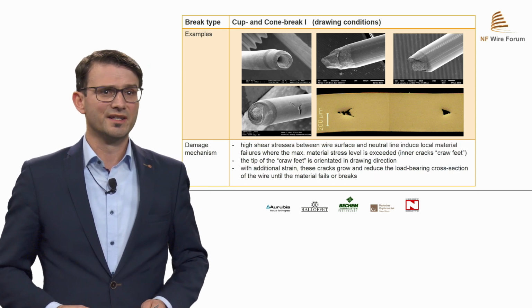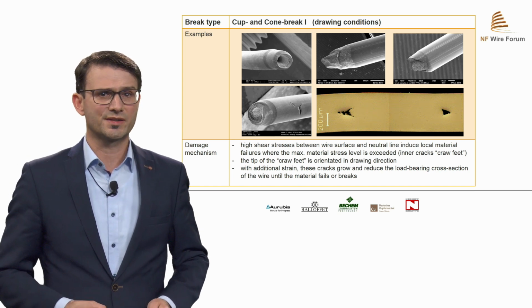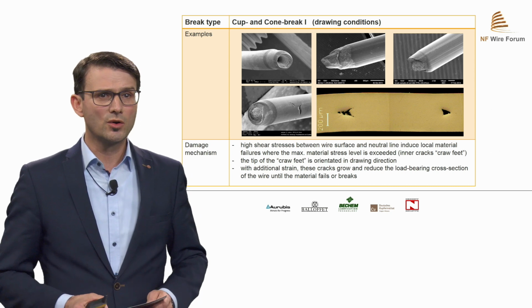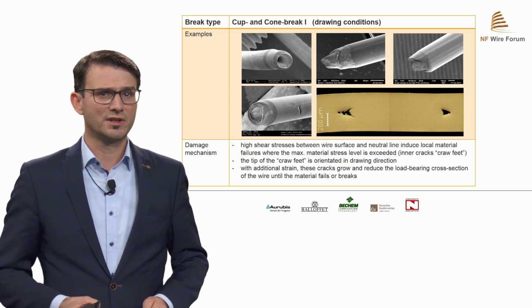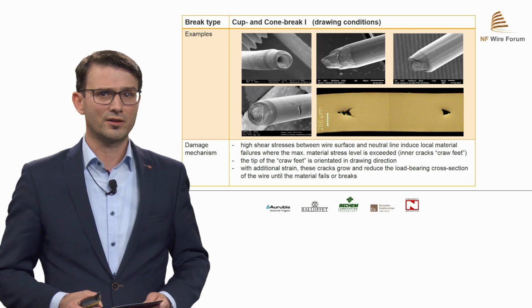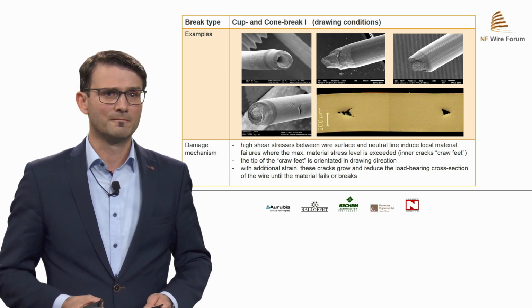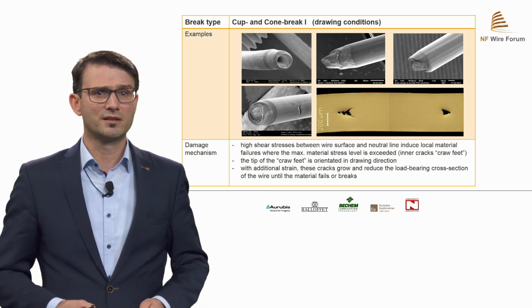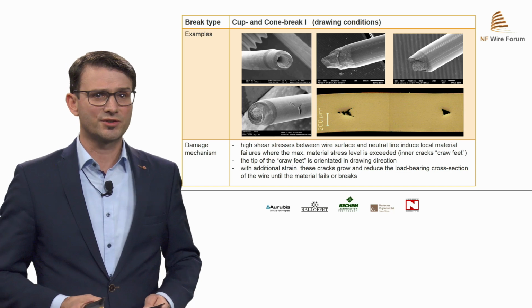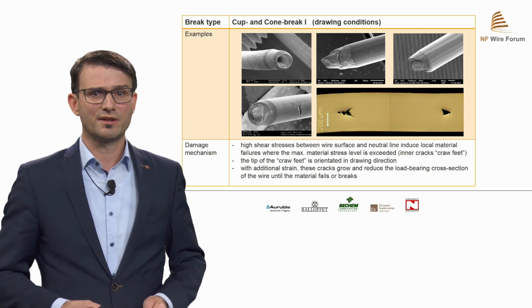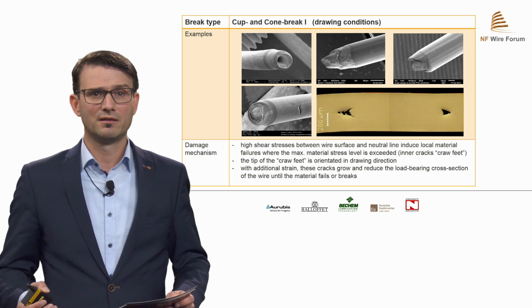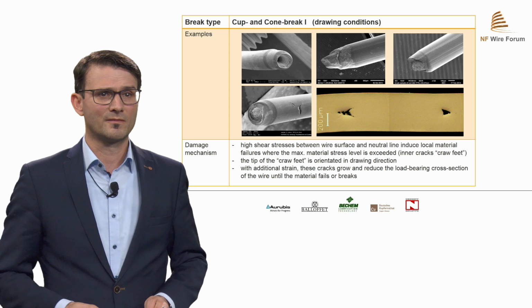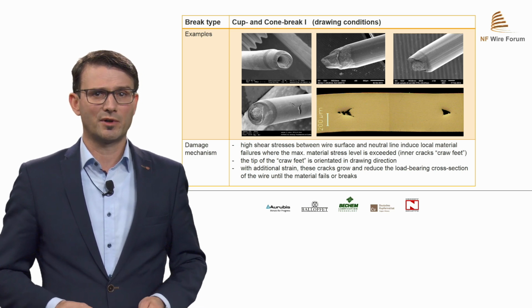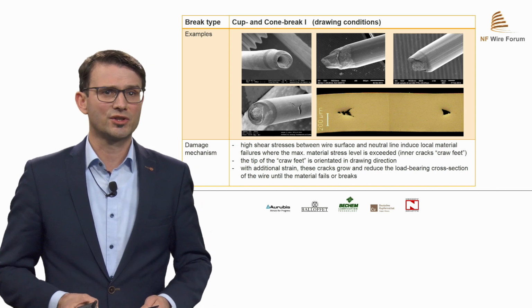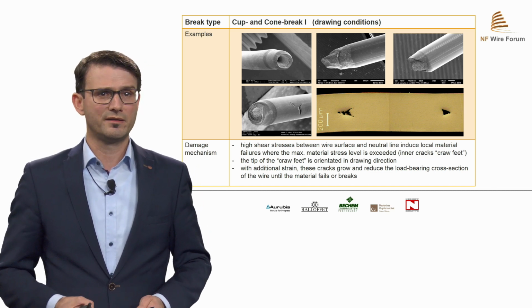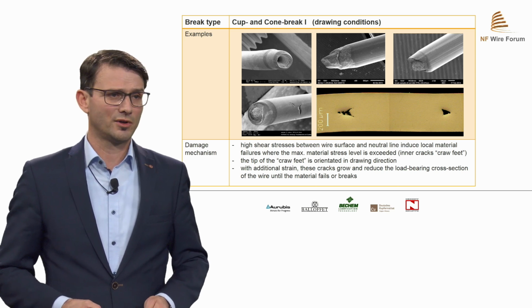What are the damage mechanisms? High shear stresses between wire surface and the neutral line induce local failures where the max material stress level is exceeded. Then the inner cracks, the crow feet, begin. The tip of the crow foot is orientated in drawing direction. With additional strain, these cracks grow and reduce the load-bearing cross-section of the wire until the material fails or breaks. As well, the copper wire rod can influence cup and cone breaks, but that is the reason, mentioned at the beginning of my presentation, to define and apply the appropriate production criteria to avoid cup and cone breaks.